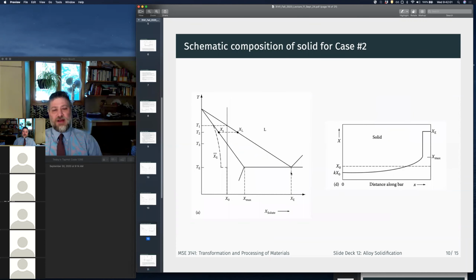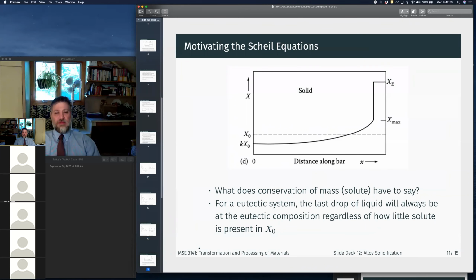So if we look at our phase diagram, the eutectic is going to have the lowest melting temperature. So we're going to have to hold this at some value that's close to here, as hot as possible, and allow the solute to diffuse, to homogenize the composition in our part, right? So this happens in steel plants, steel mills every day, right? And this was the advent for concepts like continuous casting that we'll talk about in a bit, okay?